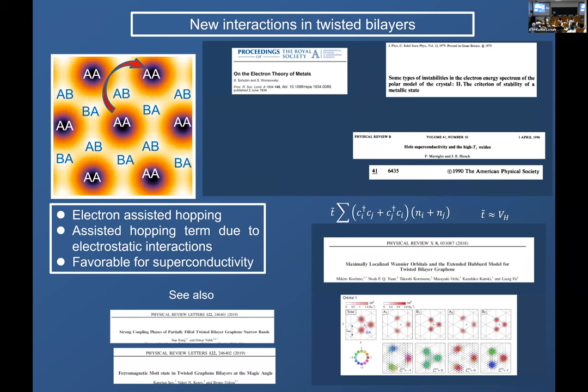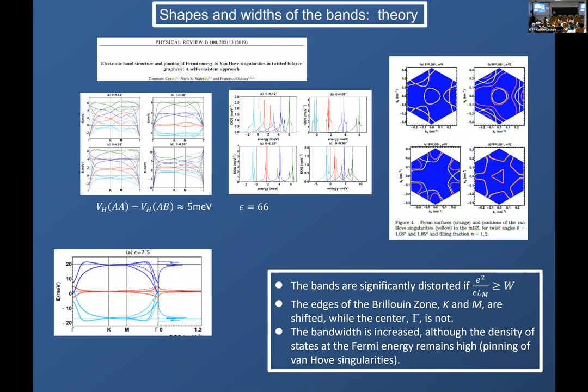That defines for you—this change in the shape of the bands implies like an effective interaction. If you try to define effective interactions in terms of a local picture, you have what one could call correlated hopping, namely how the interactions change the very tight binding parameters which determine the shape of the bands themselves.